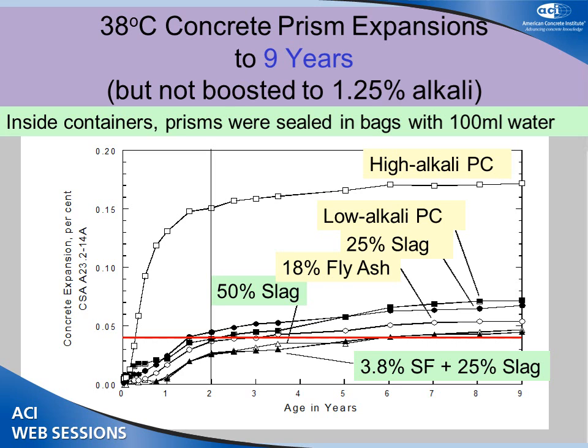The low-alkali cement was right on the border of that 0.04 at 2 years, but eventually climbed up higher, as was the 25% slag, slightly higher than the limit. The 18% ash was in the same ballpark as the low-alkali. The 50% slag and the ternary blend are the ones that are the lowest on there, the pair that are the lowest. But even if you carry it out to 6 years, they creep up there, 0.04, 0.05, but they're really not doing anything compared to, as you can see, the range.